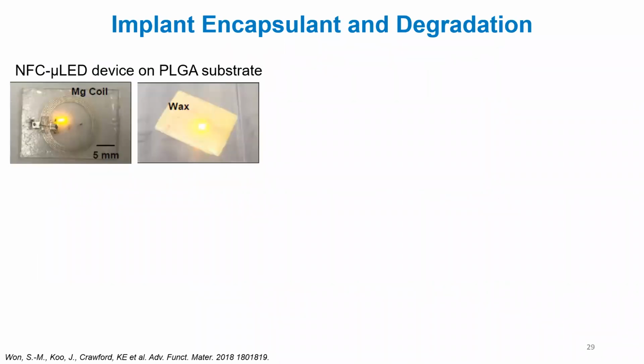So as a proof of concept, we used PLGA, the polylactic-co-glycolic acid, and we used a magnesium coil, and we used a conductive solder, using a paste, actually. So we used the wax and made a paste out of conductive material. So the only thing that's really not resorbable or biodegradable is the LED that we put on here for demonstration purposes. And then we encapsulated that with our candelilla.